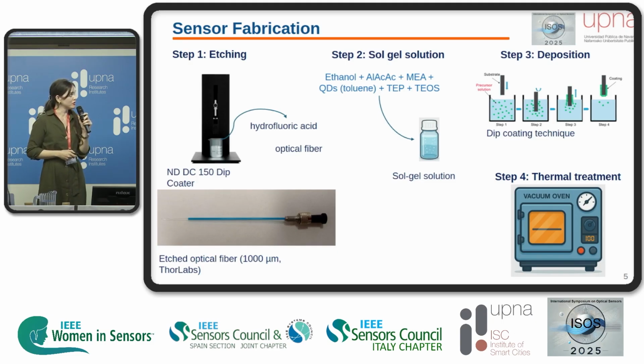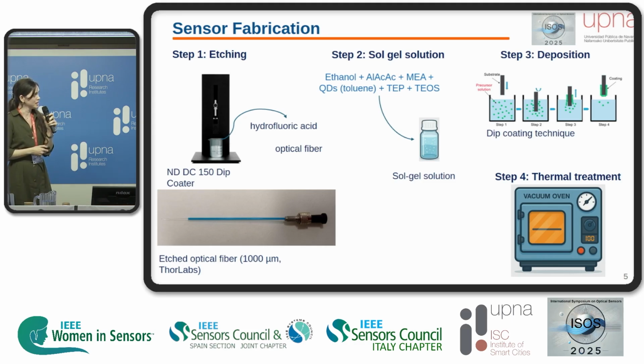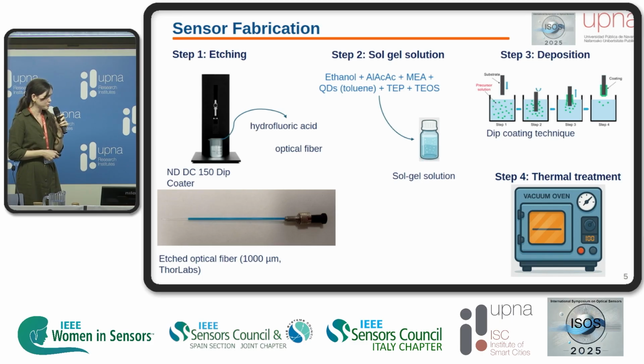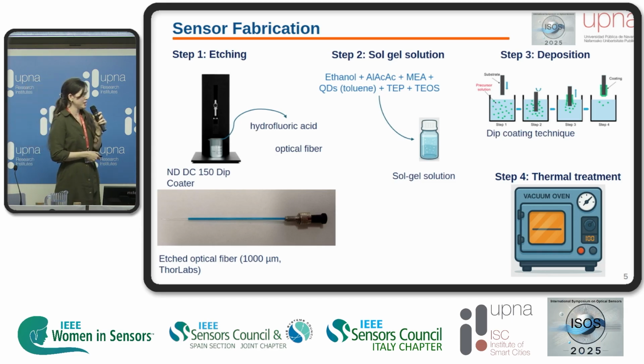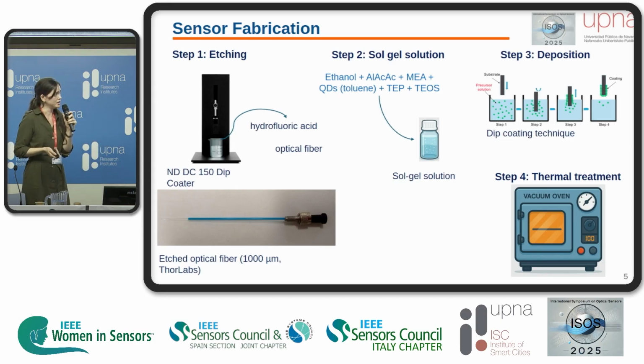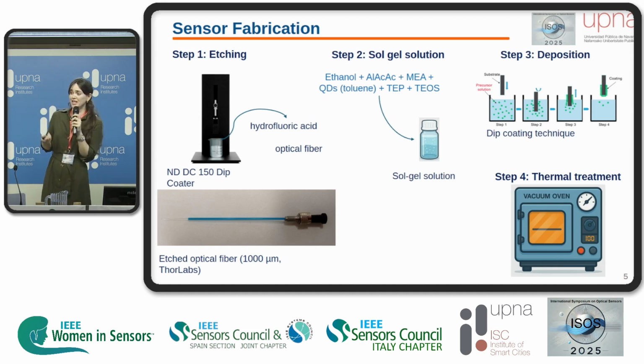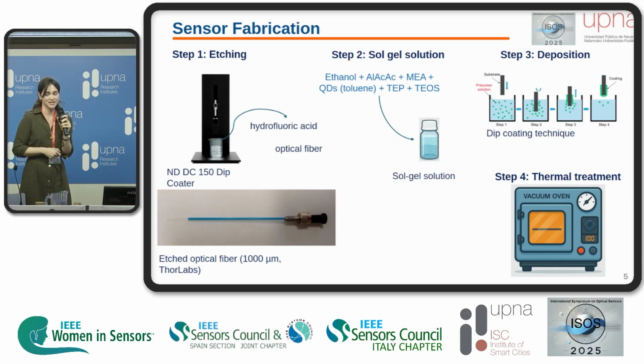The sensor fabrication process includes 4 steps. Step 1 is etching the tip of the optical fiber with hydrofluoric acid. With the dip coater robot, we taper the optical fiber to enhance the light coupling in the reflection configuration and the interaction between the fiber and the deposited material.